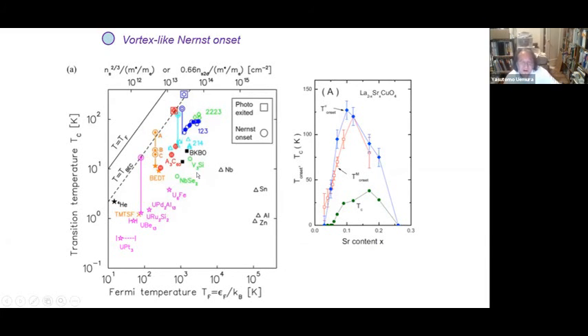And also, as Andrea mentioned, the Nernst effect was measured on BEDT organic superconductor, and the highest onset temperature of that Nernst effect is here. And also, if you look at the Nernst onset temperature, for example, for URu2Si2, the point is here. So we have at least 4 actual examples of this hypothetical Bose-Einstein condensation line seemingly observed as the onset temperature of the Nernst effect.